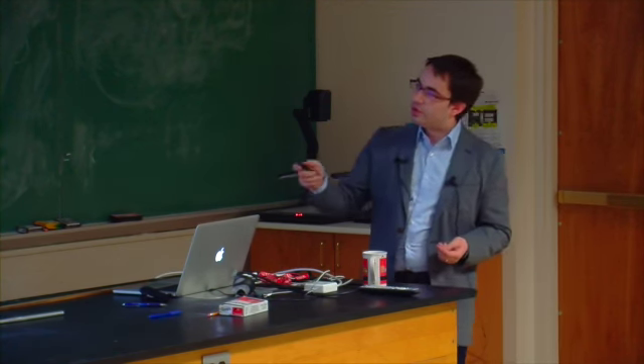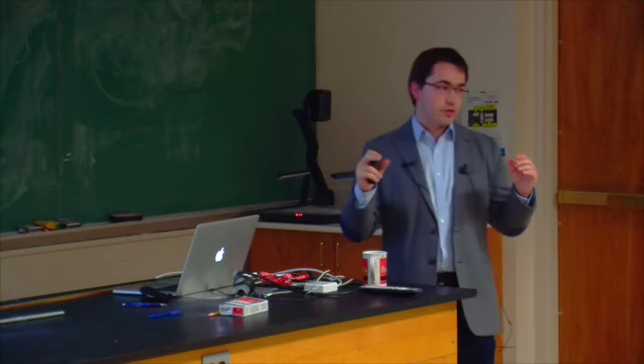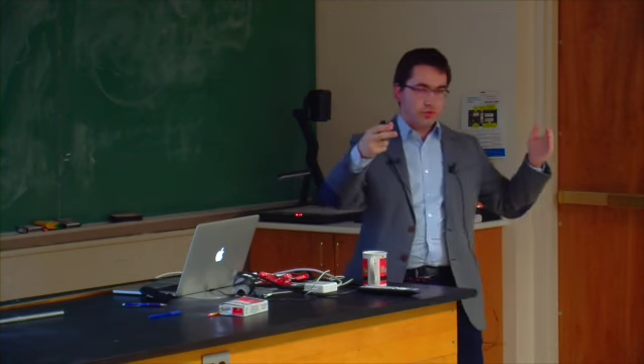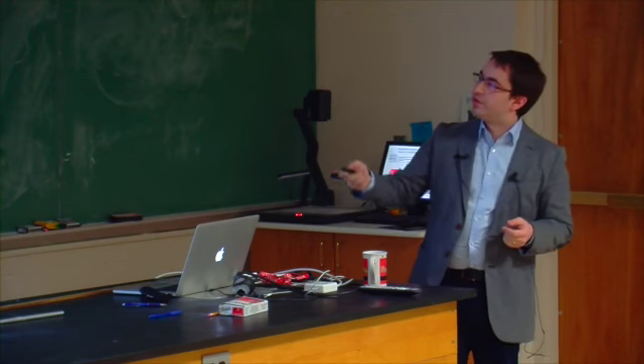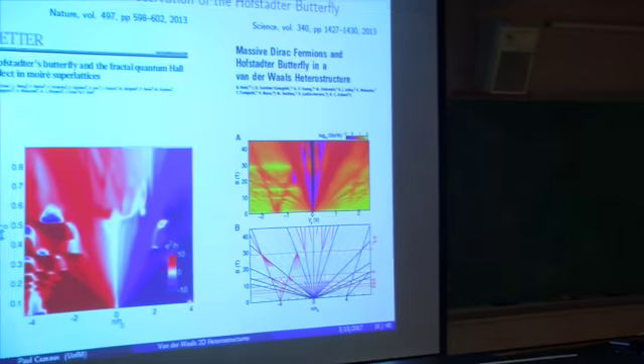This is the work of Philip Kim in bilayers of graphene on top of a layer of boron nitride. The boron nitride has a slightly different lattice constant. This provides us also with a Moiré pattern. This is what is probed here. Here, this is just a monolayer also on top of boron nitride. This also introduces a Moiré pattern on which we can probe the Hofstadter butterfly.